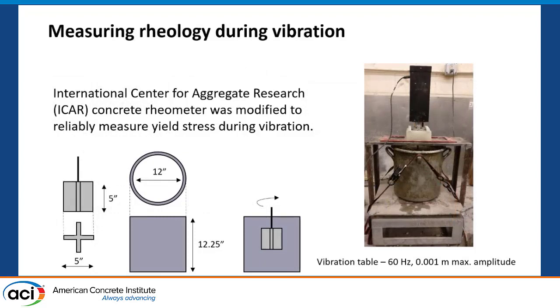How do we do that? Rheometers are generally not meant to be vibrated. So what I did was I took an ICAR rheometer, placed it on a vibration table, and suspended the torque meter which records the readings slightly to reduce the vibration noise. The way rheometers work is you suspend a vane within the material and rotate it at a constant speed. The torque necessary to maintain this constant speed can be related to the yield stress of the material.